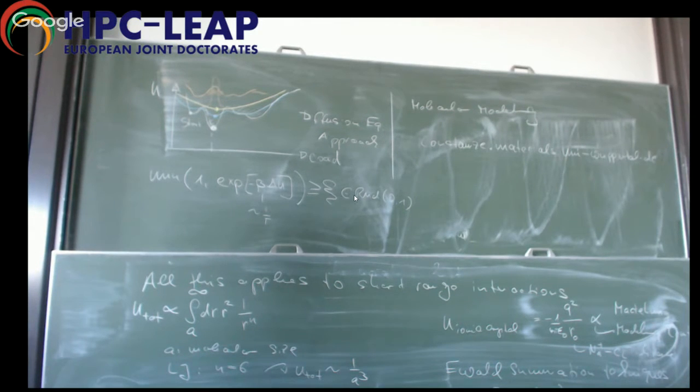One thing I wanted to point out previously was when you rotate around a bond, this is what I meant. This piece of the molecule makes a large circle, and it would hit immediately some other molecules around. So when you do a Monte Carlo on something like this, you have to try to make other types of moves, crankshaft moves, where a whole group moves in a way so that the rest of the molecule stays basically put, which is sometimes difficult to do.